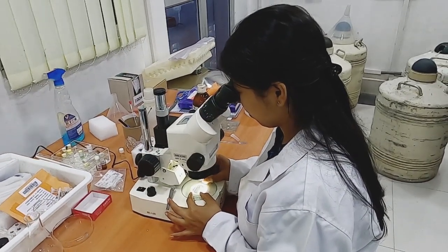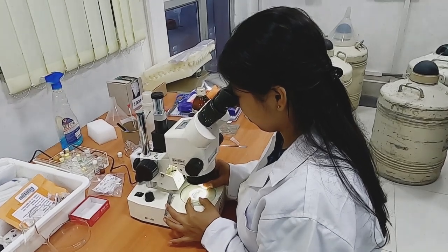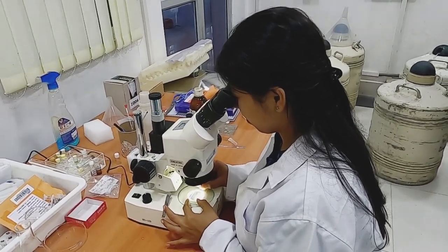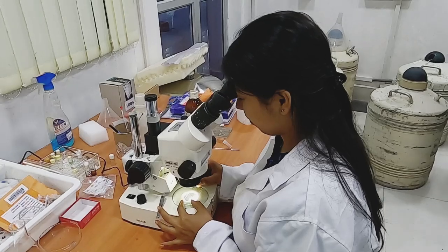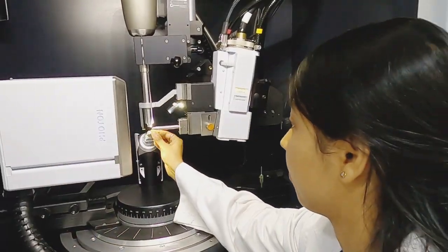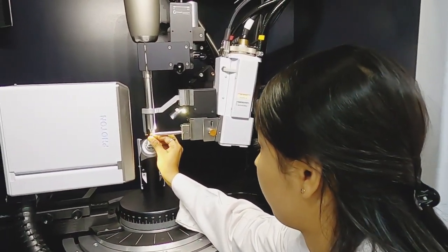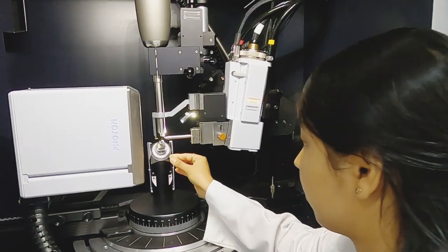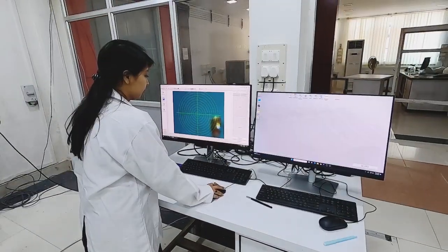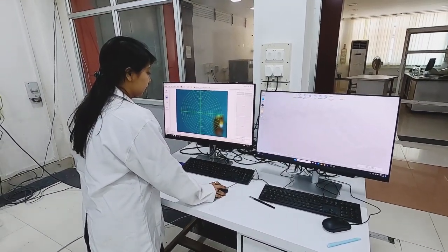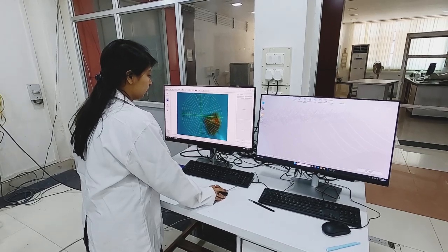My third objective deals with the synthesis of a ferrocene-based palladium NHC complex. This complex was characterized by various spectroscopic techniques, and the molecular structure of the complex was established using single crystal XRD technique. The complex showed a 4-coordinated square planar geometry where the palladium center is strongly bound to the carbene center.